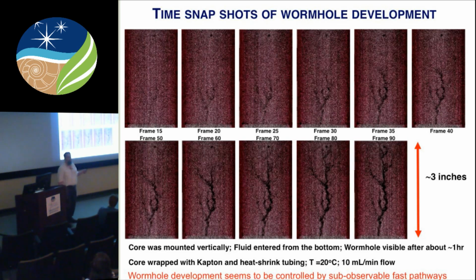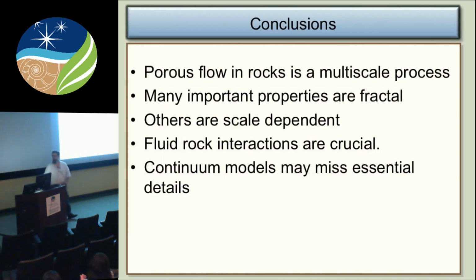Instead of drilling its way through, what's happening is the acid is moving along grain boundaries and forming an original path. If you try to model this material as a continuum, you will not reproduce what's really seen in the real rock, because the grain boundary flow paths are what is really controlling how all this reaction occurs. And without that, the model can't reproduce dissolution in real materials. As I said, this is really new data, and we'll just leave it at that.